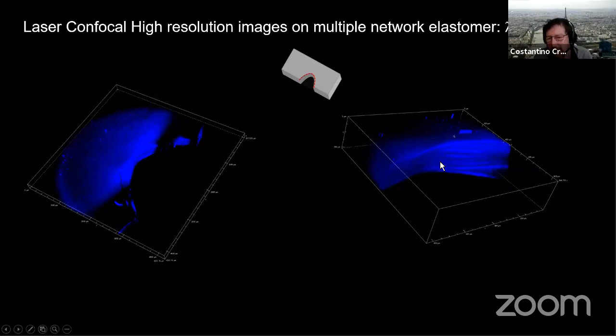There is one thing that you can see in the picture on the right. You can see the filaments. So you can see that the damage is very much 3D. Of course, your crack tip is not a 2D problem. It's a more complex 3D problem. Now, if you see these images, on the other hand, you can immediately think that quantification is a bit tricky. I mean, how do you know how many bonds you've broken? Where do you put the limit? You have many bonds breaking in the bulk. So maybe, for such a sensitive molecule, we could actually tackle networks where the bond scission is much more localized. And that was really the idea.